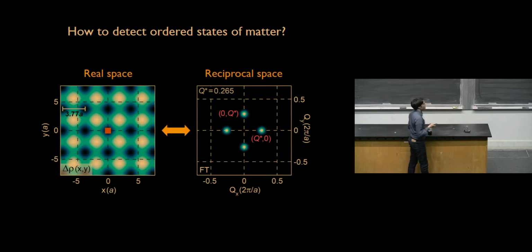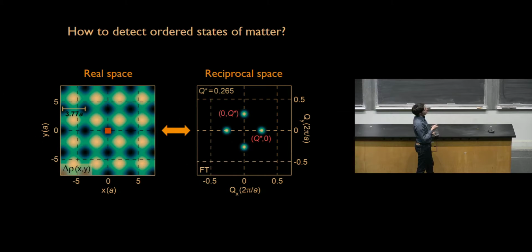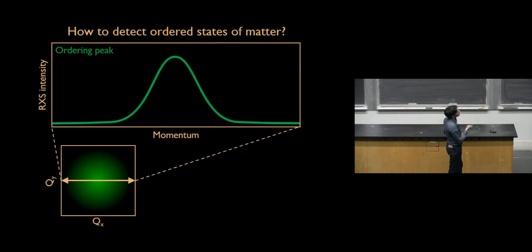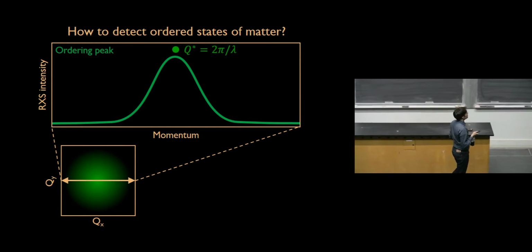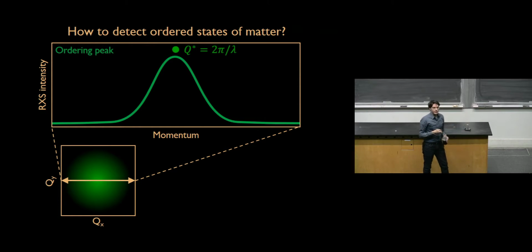So that's exactly what we do in our experiments. Instead of looking at the real space, which is something that some techniques do, like microscopy, we look in reciprocal space, and we focus on one of these peaks, which I'm now showing here, and we slice across it, and then we see this peak as a function of momentum. So this is the momentum axis. This is some kind of intensity that we measured in the lab. And then the position of this peak, say Q star, is equal to 2 pi over the wavelength.